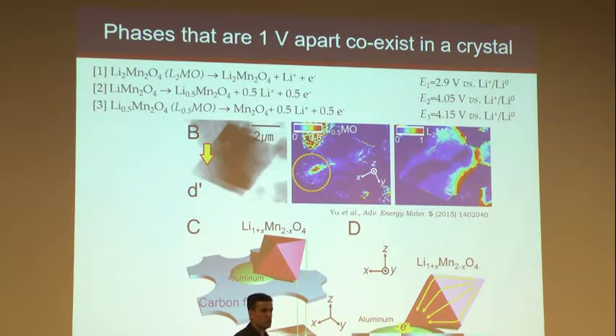They're far from each other, but this is a 4-micron object. And look at the difference in potential between the two. Lithium 0.5 exists at 4.05 volts. Lithium 2 exists at 2.9. You have a potential drop across your particle that is over a volt. So this was one of those things where you look at the data and say, yeah, this just can't be. This must be wrong. I can show you the spectra if you want to see it. There's no other way of explaining it.